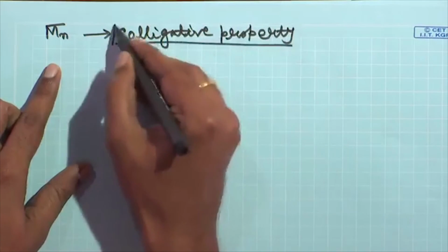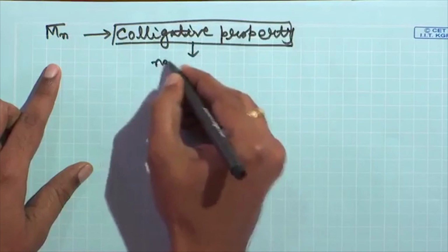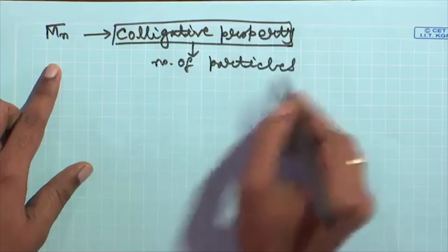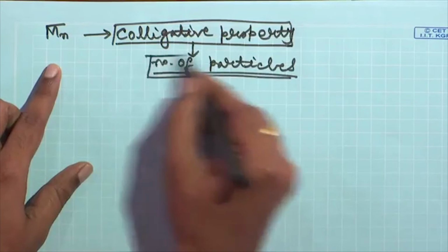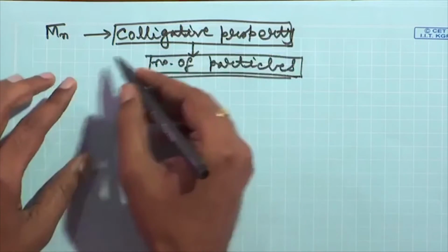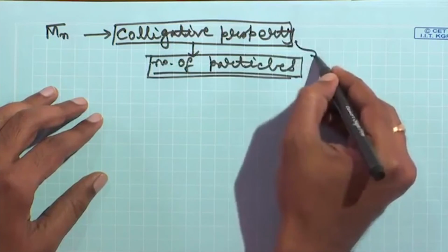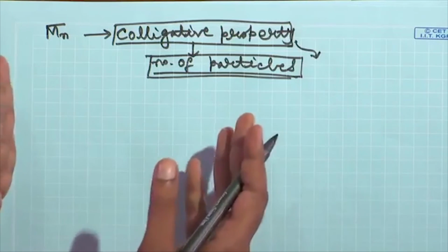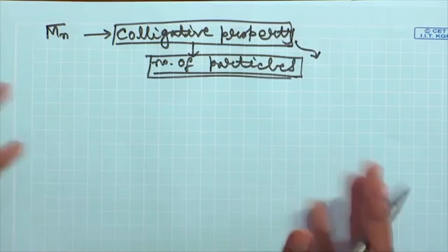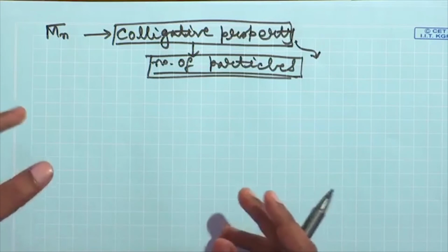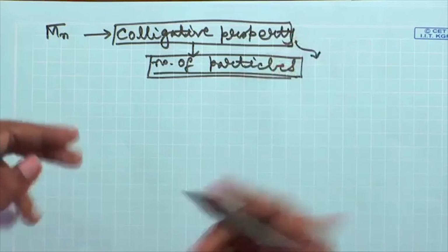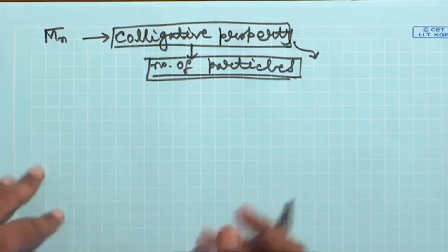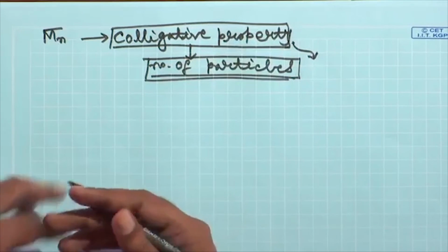Now, you know these colligative properties depend on the number of particles of the solute present in the solution, and so these kinds of experiments are biased towards the low weight fraction part of the sample, because your sample, as I told you, can have say 90% of polymer molecules which have very high weight, and maybe 10 weight%, the rest, of low weight.